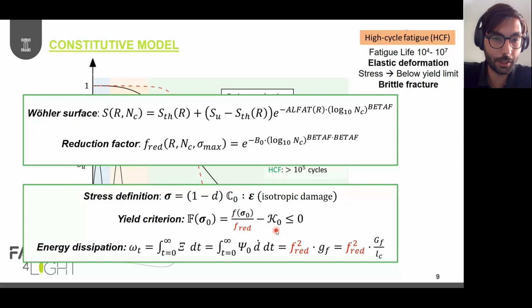So if the strength is greater than the stress, this is lower than 0, so we are in elastic regime, everything is linear. But if not, we have to account for any means of degradation, in this case damage. Fatigue is introduced in this model by dividing the normal stresses that the sample is exhibiting by this reduction factor that initially is 1, but along cycles the f_red will be reduced. So it means that the stresses will be amplified in order to accumulate this degradation due to fatigue.